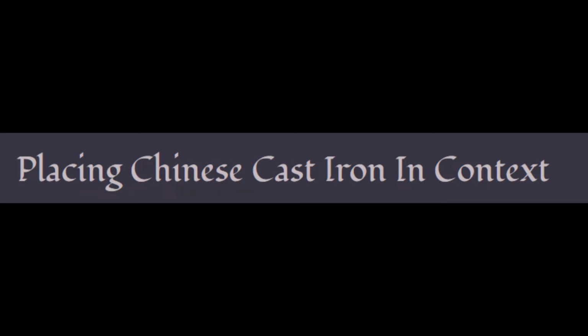This may explain why, despite the potential for the malleabilization process, if performed with the iron fully molten, to produce iron with functionally no slag and very uniform carbon content, Chinese malleabilized iron never gained the reputation as a superior product that Wootz so clearly enjoyed.